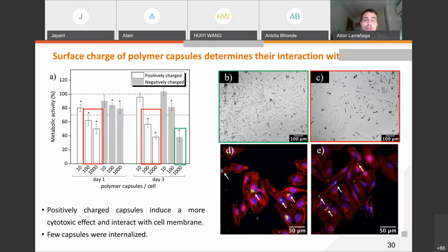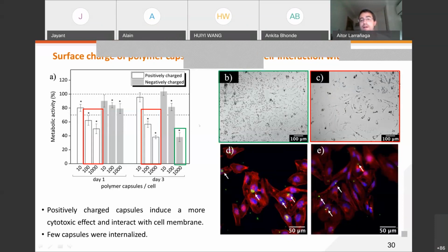The situation was quite different when we worked with the negatively charged polymer capsules. In this case, we only observed a clear cytotoxic effect when we were working at the highest concentration. And as you can see here in this micrograph in green, the interaction with cells was completely different. It was not as strong as in the case of the positively charged capsules. As you can see, all the capsules appear quite well distributed in all the cell media.